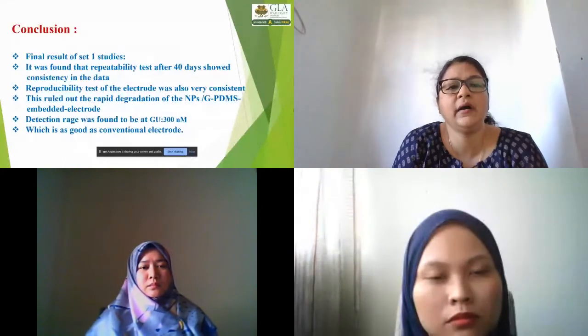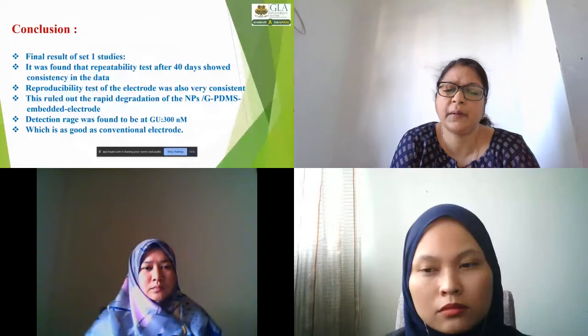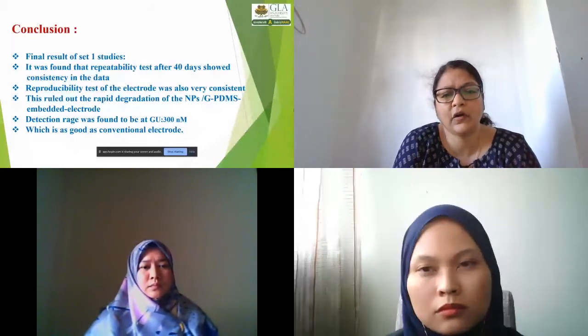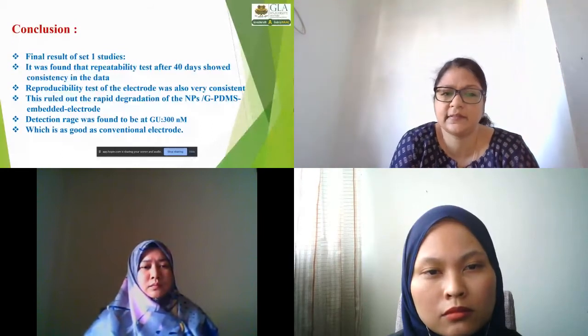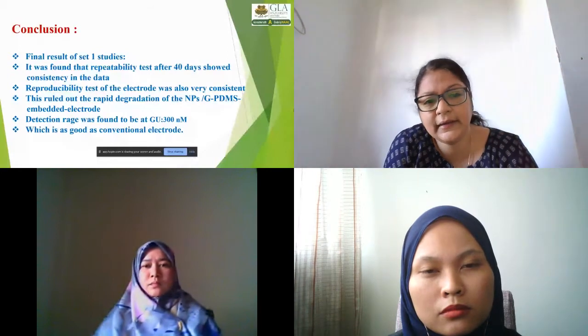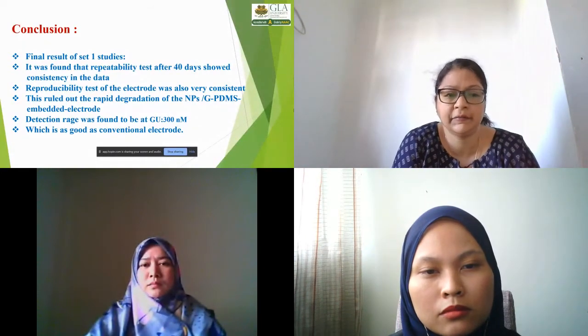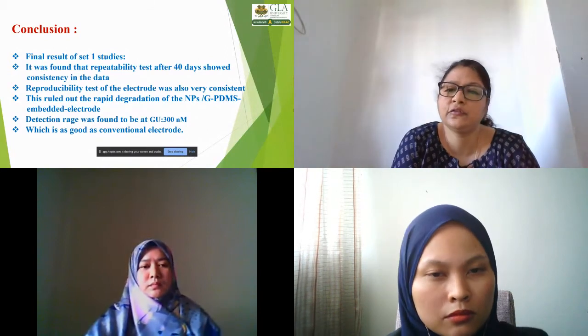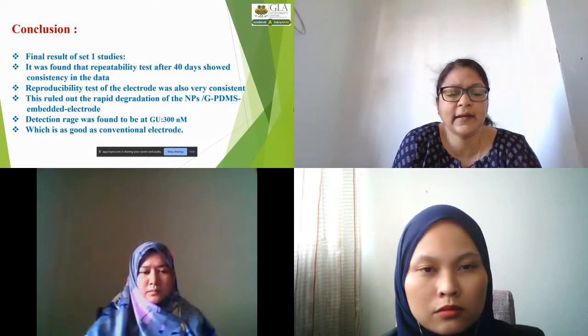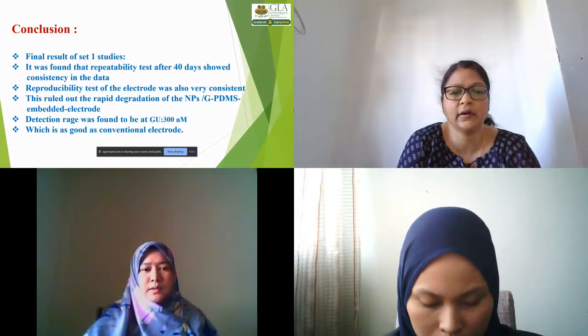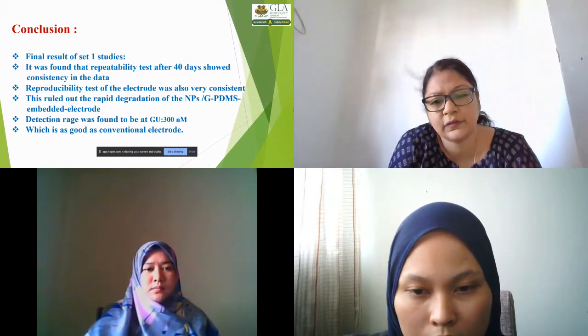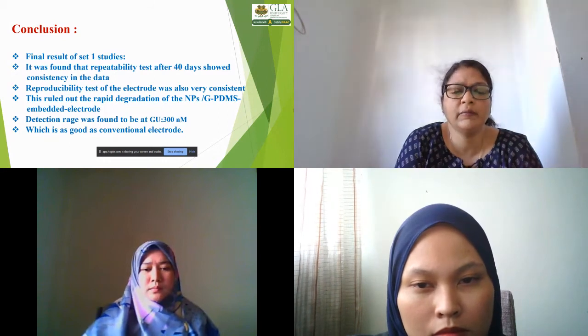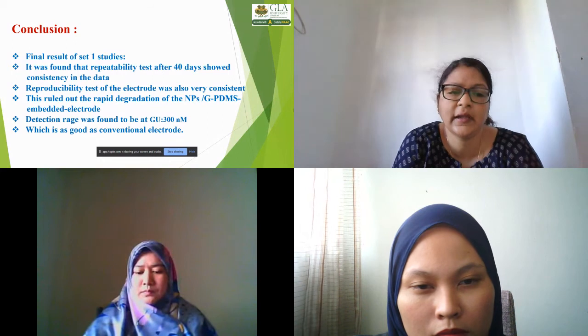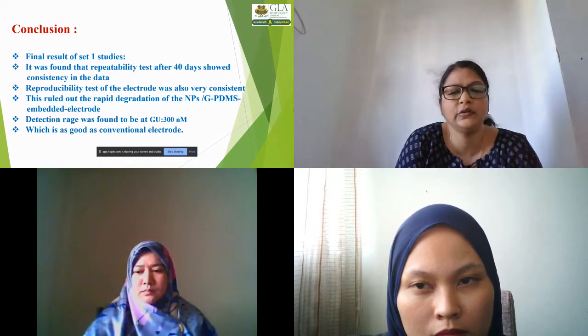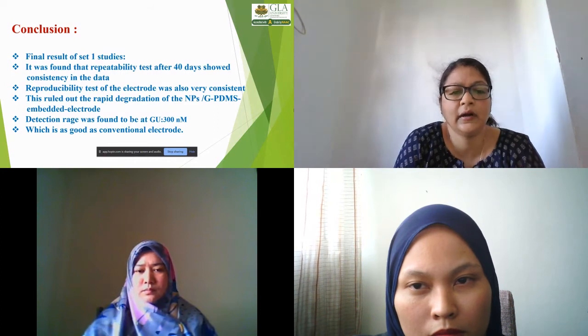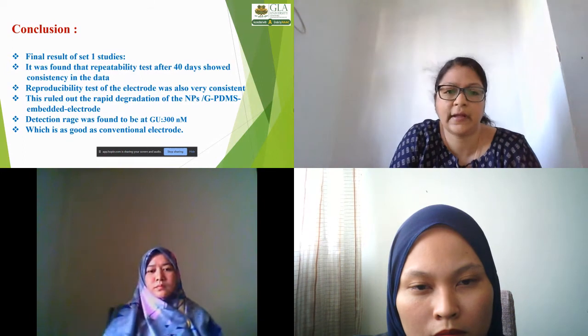So in conclusion, in the first part of the project, we found that after 40 days, when we performed repeatability tests, there was consistency in the data. A reproducibility test was also done using a freshly prepared electrode, and that also showed very consistent results. So we realized that degradation of the electrode is not taking place, and the detection range that was found was around 300 nanomolar. Conventional solid electrodes gave around that much value. So we understood that this polymer electrode is also giving good values.